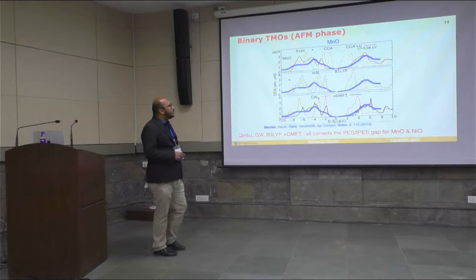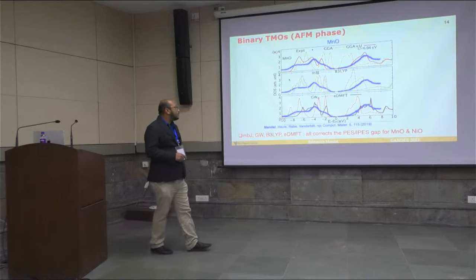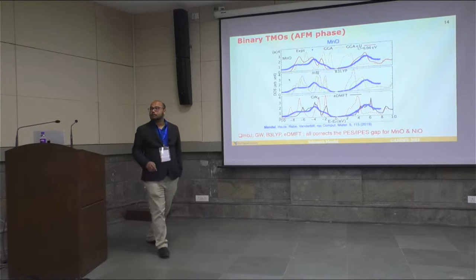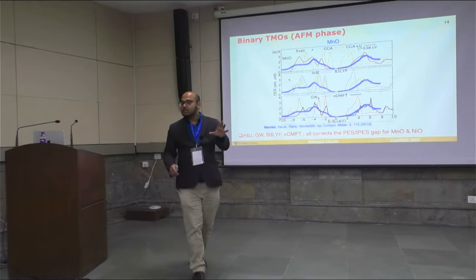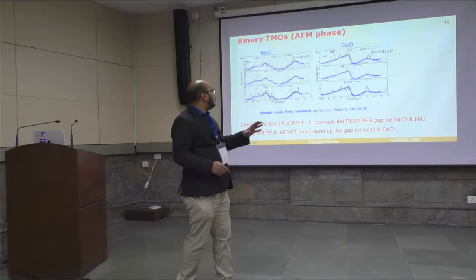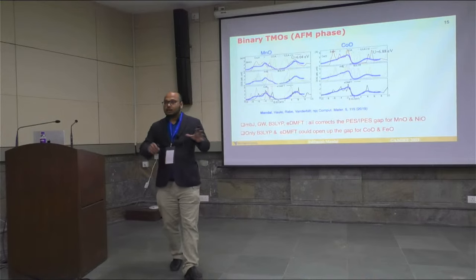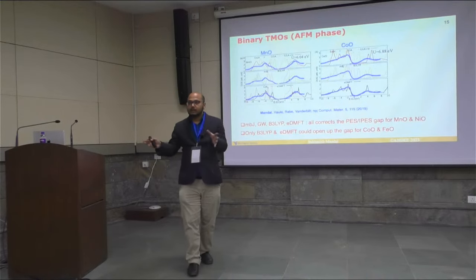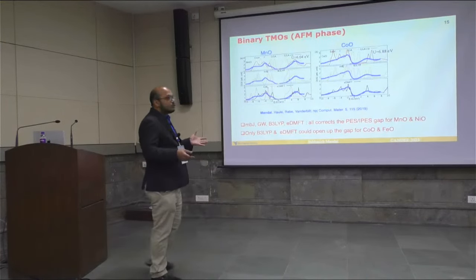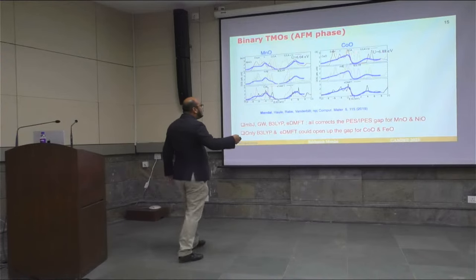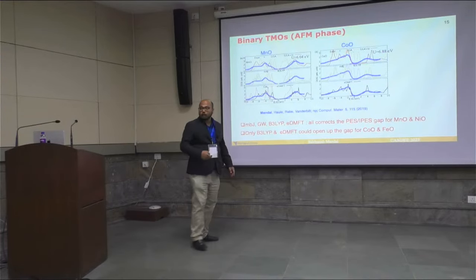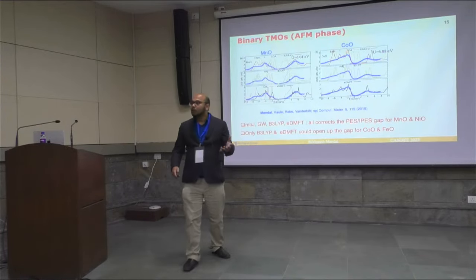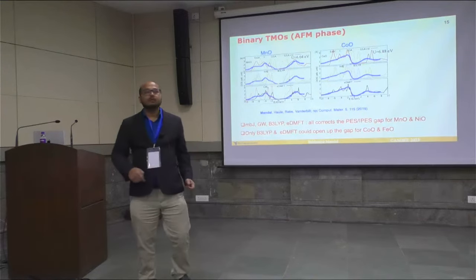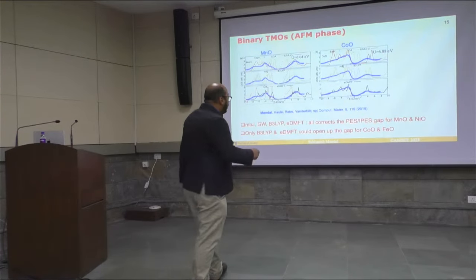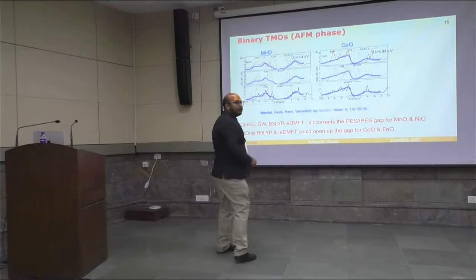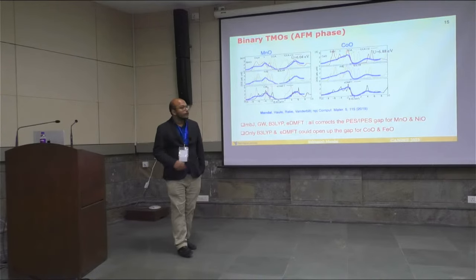For mBJ and B3LYP, it also works. GW and so does DMFT. So it is a very similar-looking structure to MnO if you go with cobalt oxide. Your lattice model will be the same, and the same kind of physics you should expect. But then if you do GGA, it's going to show metal. If you do meta-GGA, it's going to show metal. If you do GW, it's going to show metal. Only the hybrid functional can actually open up the gap, and DMFT.